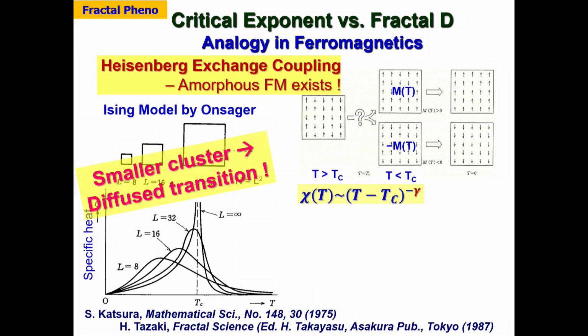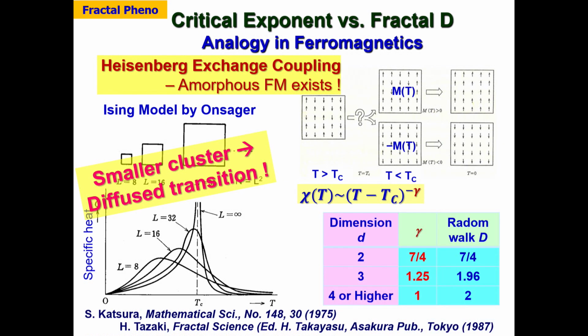For smaller clusters, a diffuse phase transition usually comes from the Heisenberg exchange coupling. But you may know that amorphous ferromagnetic materials are widely commercially available. This is totally different from ferroelectrics, like the Coulombic energy stabilization. For the permeability or magnetic susceptibility with the molecular field, in a large single crystal, in that case, gamma is equal to 1.